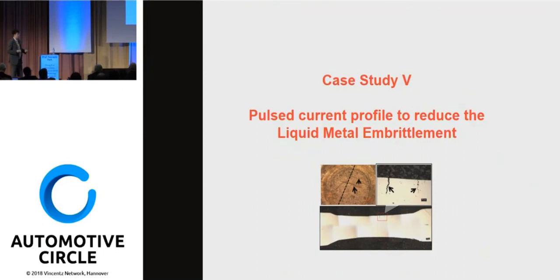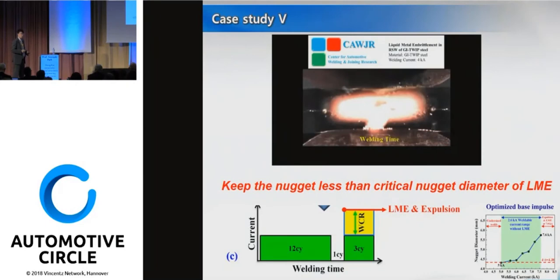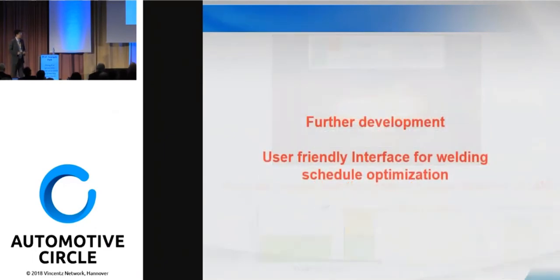The automotive and steel companies are also suffering from a lot of cracks after resistance spot welding, especially for the Gen 3 steels. This is a video I took about 4 years ago. There are a lot of LME cracks happening during resistance spot welding. Then this is another current profile which I applied, but we still need to keep the nugget less than the critical nugget diameter for LME.